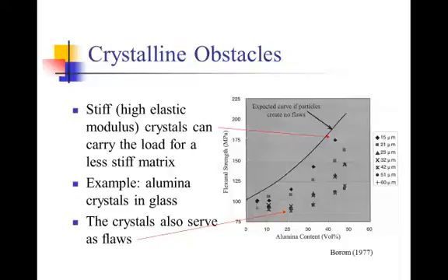And that's why if we introduce only a little bit of crystals in the material, we actually see a small decrease in the strength. And then as we begin to increase the amount of crystals that are present, the stiffness of them has more of a benefit than their presence has detriment to the strength of the material, and we end up with a stronger material, especially in the case where we have very small crystals, and so their addition doesn't serve to create large flaws in the material.